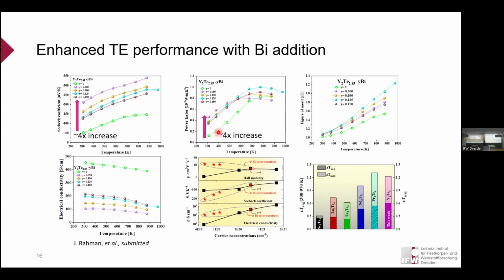Following the whole measurement, we can try to understand what the mechanisms are here. And basically what we can see is that after bismuth incorporation, the mobility has been greatly improved in comparison to the bismuth-free compounds. So at the end of the day, we can see the figure of merit ZT has a significant improvement from initially around 0.4 by a factor of 2, reaching like 1, even 1.2. I mean, you can still see this is an increasing trend. So it means it could be higher at even higher temperatures. Yeah, that's for this part of work.